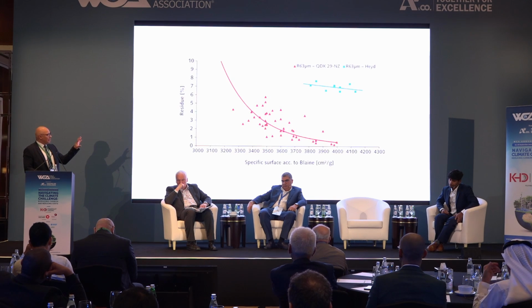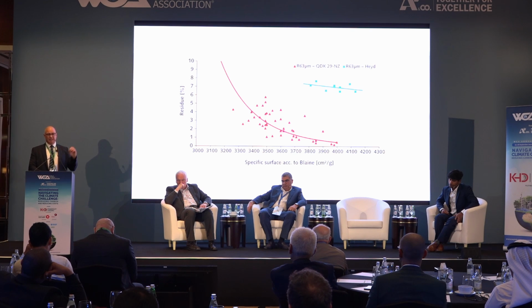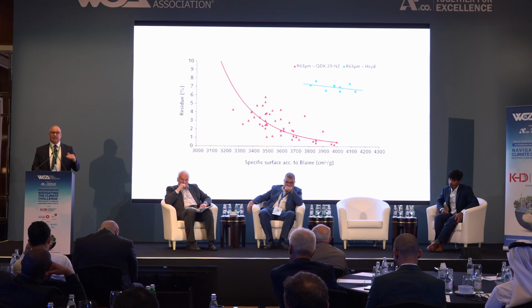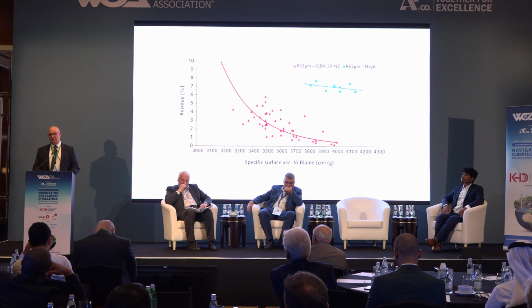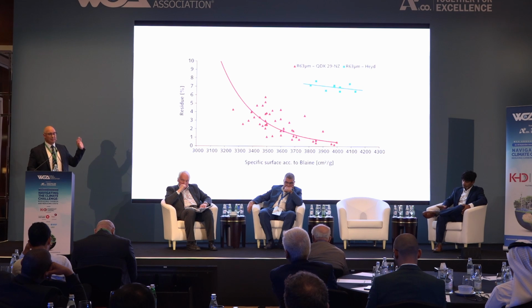And it's still called third generation, 3.1, fourth, whatever. Marketing is marketing. I'm more technical, yeah? The thing is that we can change a lot changing the separator. And we are talking about what we will do in 30, 40 years, but bringing things to the ground. I'm telling you that 70%, I don't want to exaggerate because it's a different measure, but 70% of the mill audits that I'm doing have a very low performance on the separator. So this is a relationship between the particle size distribution that we are seeing as a retain on 45 microns, 63 microns, it depends on the measurement that we are using, and the Blaine.